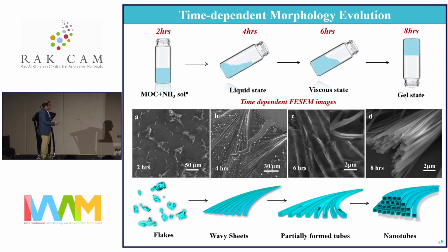To understand this, we did a time-dependent study. In the first 2 hours of the gelation process, it forms flakes, each with a nodal point. After 4 hours, it forms anisotropic growth of the nanotube. After 6 hours it partially forms the tube, and eventually at 8 hours, it forms the beautiful, perfectly aligned nanotube.